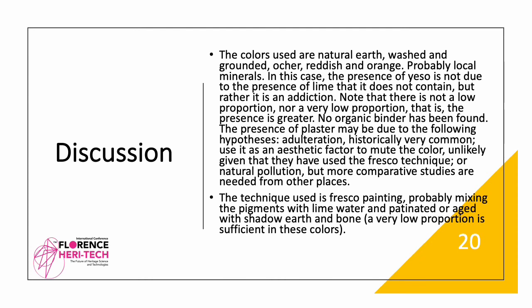The colors used are natural earth, washed and ground: ochre, reddish and orange, probably local minerals. In this case, the presence of gesso is not due to the presence of lime, that does not contain, but rather it is an addition. Note that there is not a low proportion, nor a very low proportion, that is, the presence is greater. No organic binder has been found.